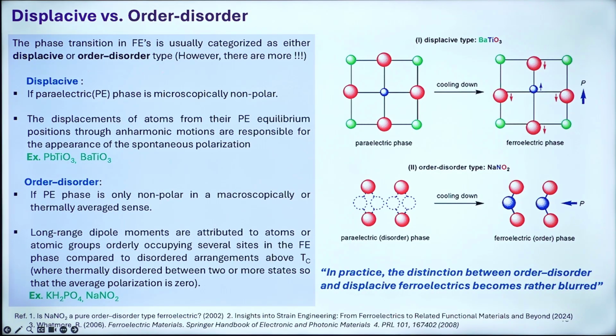NaNO2 is one such classic example, and potassium dihydrogen phosphate is another example which is purely order-disorder type. In sodium nitrite, NaNO2, the paraelectric phase is disordered, and when you cool it down, it goes to a ferroelectric ordered phase. So when you try to understand the mechanism for ferroelectricity, these two are the important criteria. One is displacive, another one is order-disorder.